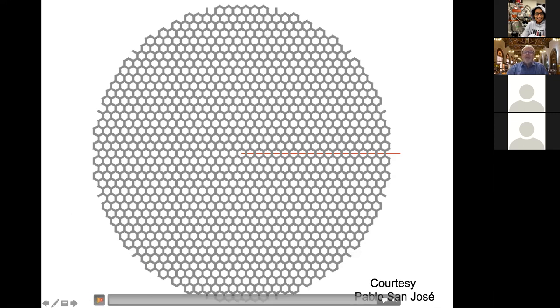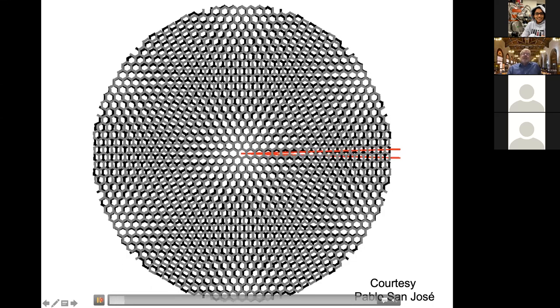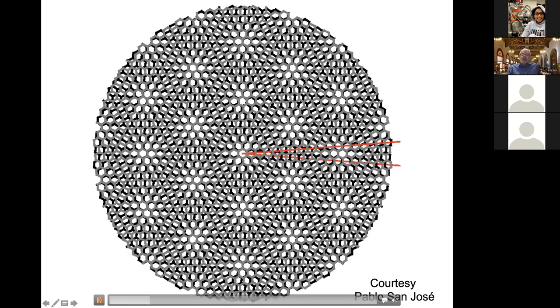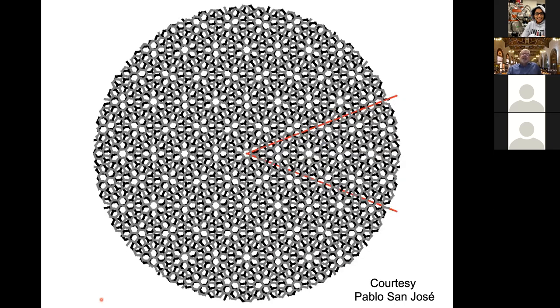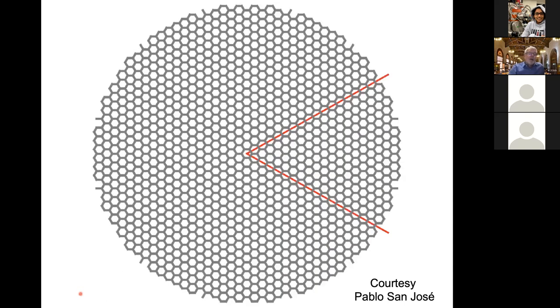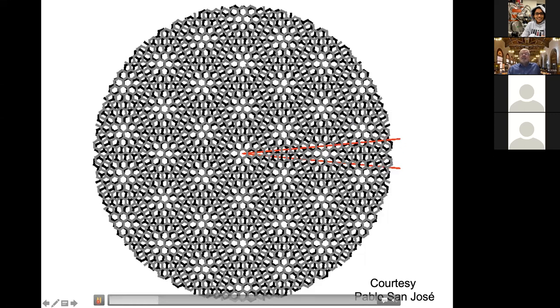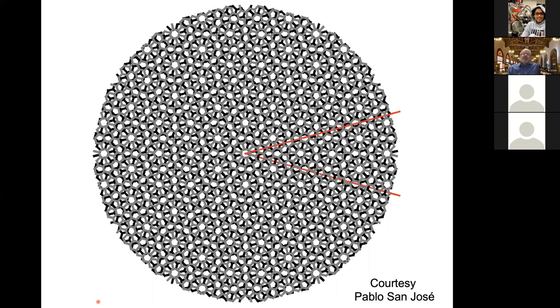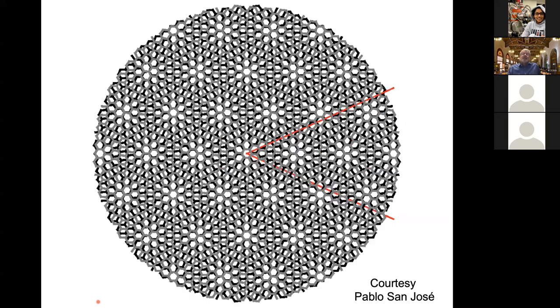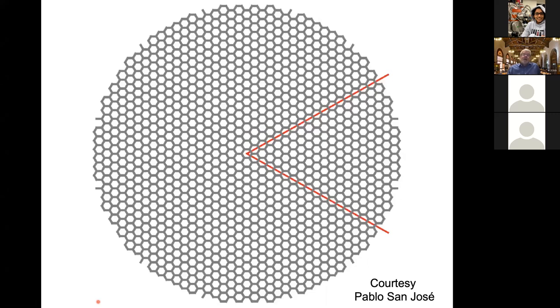But if you twist one relative to the other, then you can see that there's a spatial dependence in the coordination between the two layers, how one layer sits on top of the other. And what you see most easily are the points where locally the two layers are stacked on top of each other, so-called AA points. And if I do this again, you can also see that, in this case, we're just twisting two identical layers. And if the twist angle is small, then the coordination between the two layers changes very slowly. Technically, what you're seeing there and what varies periodically is the displacement of one layer due to rotation modulo the lattice vector of the crystal. And so it produces the periodic pattern. You can see that's called a Moiré superlattice.